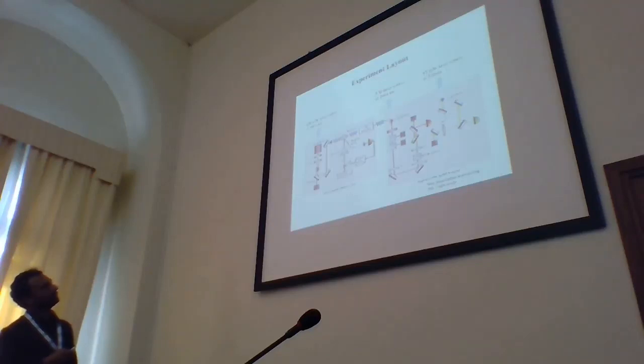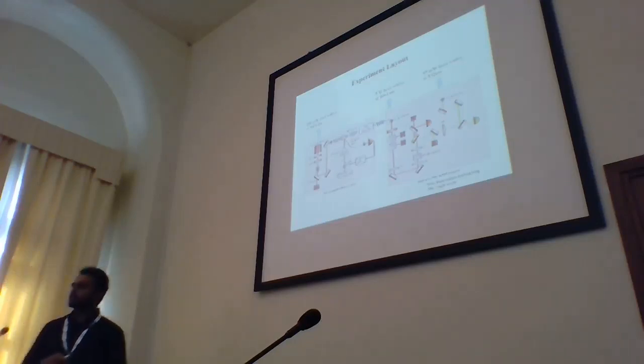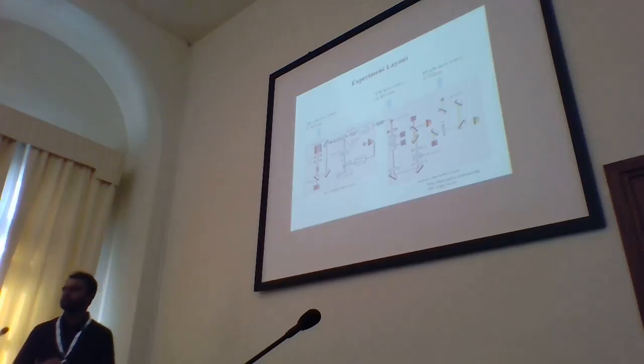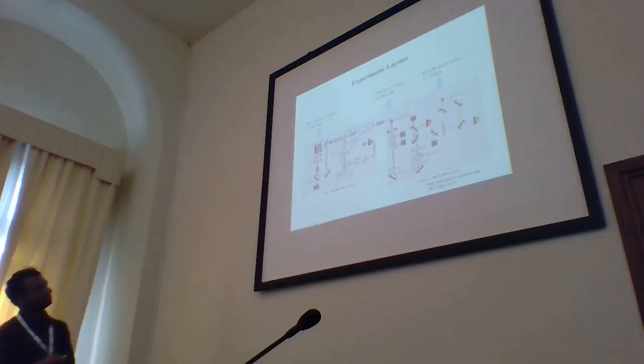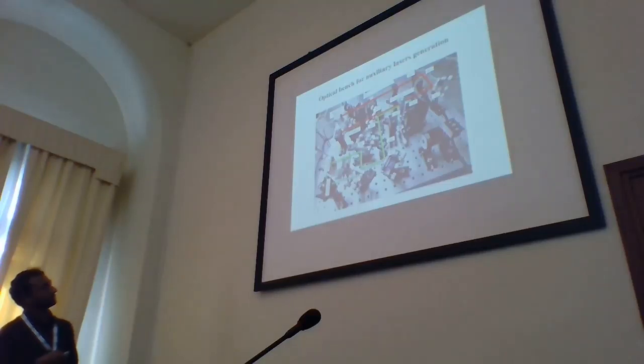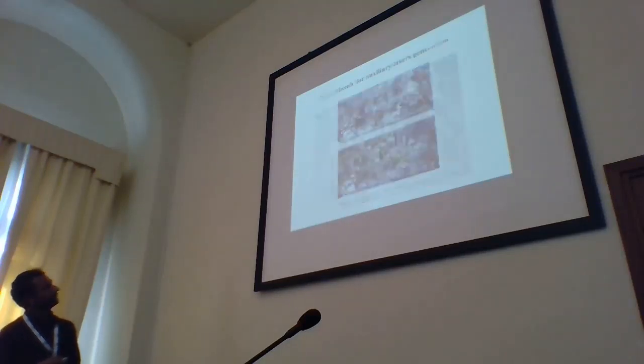Again, we have a fiber collimator that allows us to make the beam again in free space, and with some necessary optical components, when the beam passes through the nonlinear crystal, you see that along with your infrared laser light, now there is some green path. This represents your second harmonic beam. In this experiment, I was able to achieve up to 97 milliwatt of green laser power for an input of 2 watts of infrared laser light at 1064 nanometer. This is just what I explained from the bench.